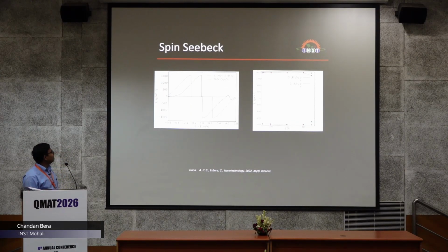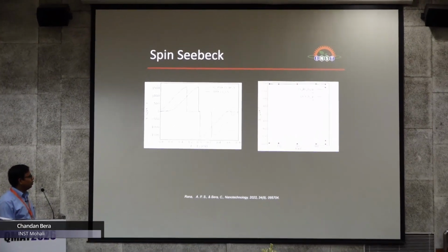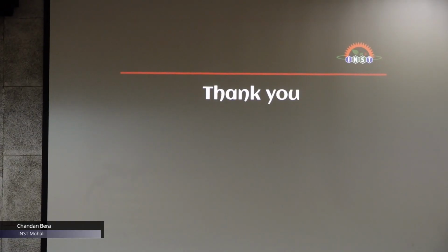The spin Seebeck effect was also calculated for these three materials, because these are also magnetic 2D materials, and we found that their spin Seebeck coefficient is of a similar value, around 1500 microvolt per Kelvin, and this remains constant from room temperature to very low temperatures.